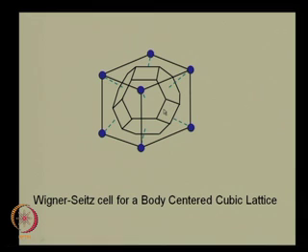For example, this structure that you see here is part of a plane that bisects the line joining the body center of this single cube that you are seeing here and the neighboring body center. So if you had continued this lattice, if you had drawn the next set of lattice points here, you would have once again found one other body center. So you can connect the body center of this particular unit cell to the next unit cell, and the perpendicular bisector of it will actually be this plane, simply because the body centers are exactly halfway into the unit cell.